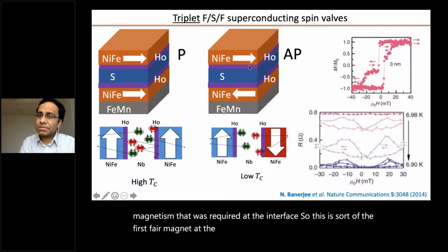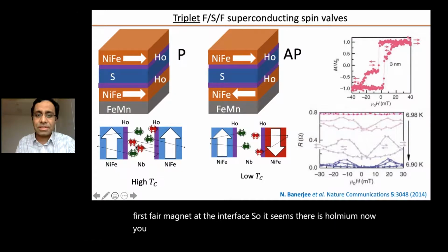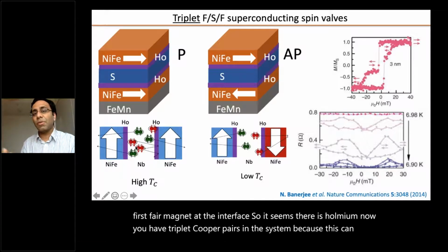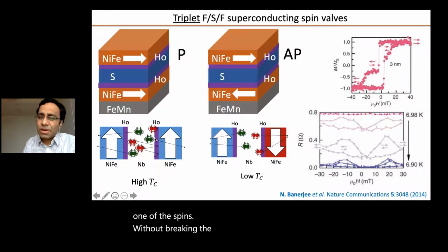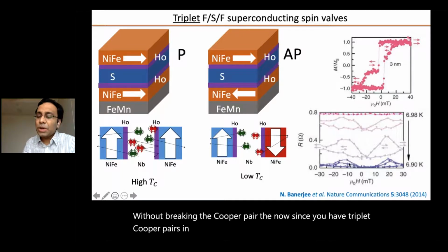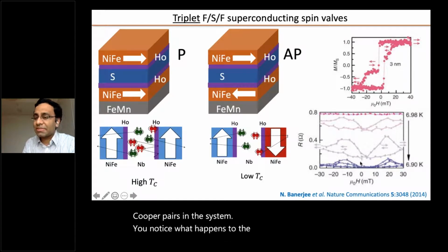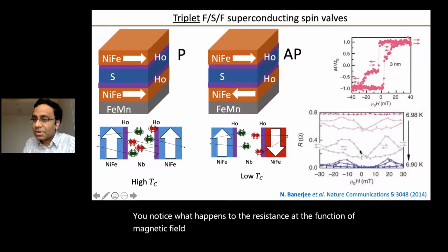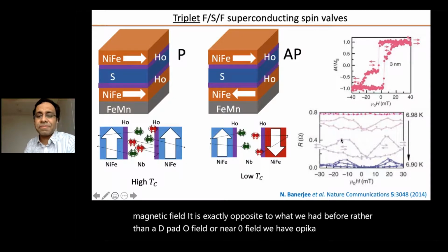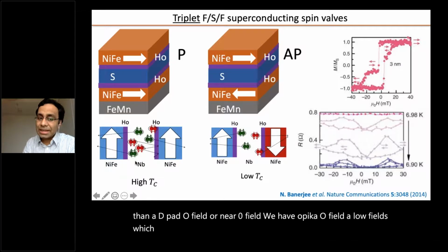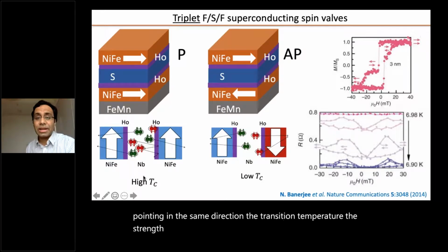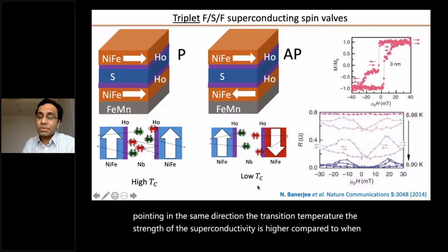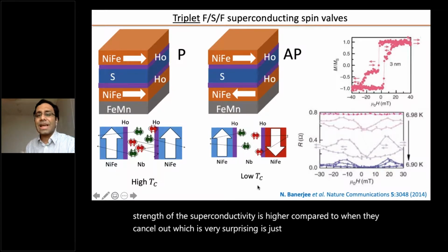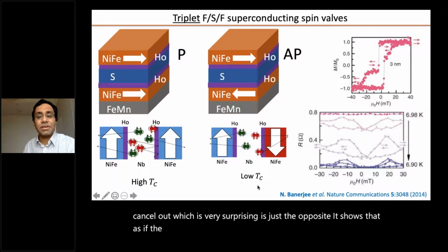Since there is holmium now, you have triplet Cooper pairs in the system, because this can rotate one of the spins without breaking the Cooper pair. Now, you notice what happens to the resistance as a function of magnetic field. It is exactly opposite to what we had before. Rather than a dip at near zero field, we have a peak at low fields, which means that if the magnetic moments are pointing in the same direction, the strength of the superconductivity is higher compared to when they cancel out, which is very surprising. It's just the opposite. It shows as if the superconductor likes the magnetic field rather than seeing a low magnetic field.